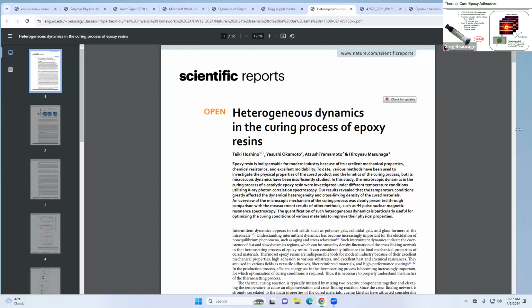So we literally just threw that thing into a temperature cell and ran it through a pre-cure step, and then ramped it through this thermal cure, where you heat it up really rapidly and then hold it at 120 degrees for 30 minutes. That's what it says on the bottle, that's how long it takes to cure. So we wanted to validate and see, could XPCS also give us information about that curing process at the nanoscale, rather than at the macro scale, which is the typical type of experiment we would do?